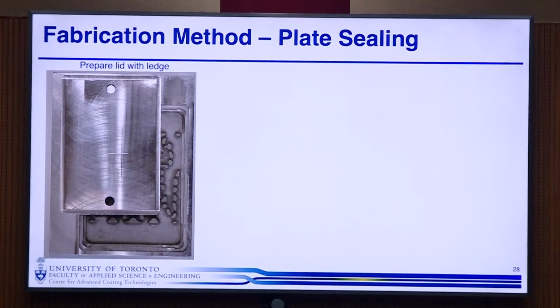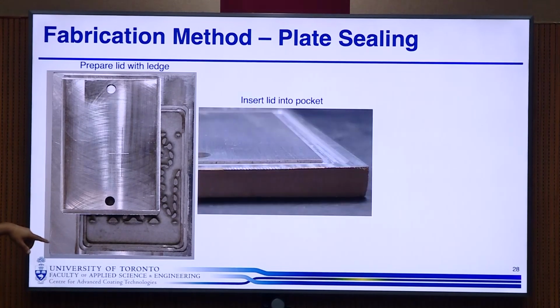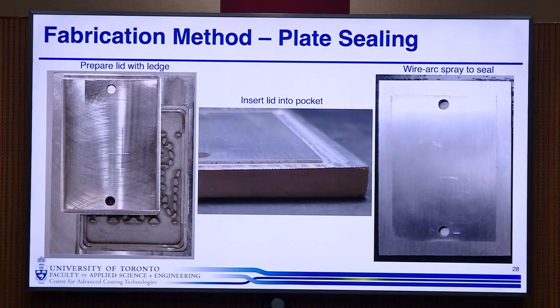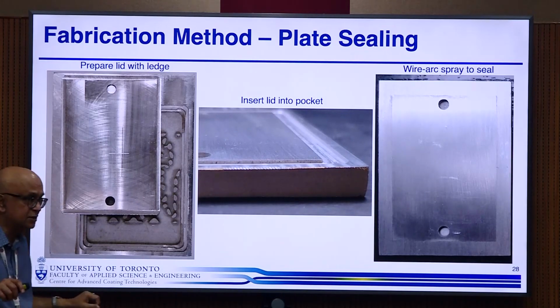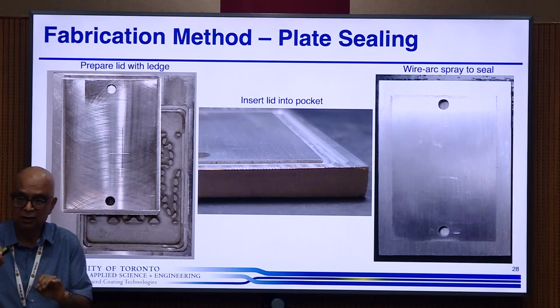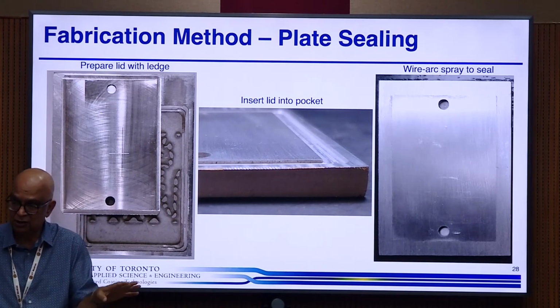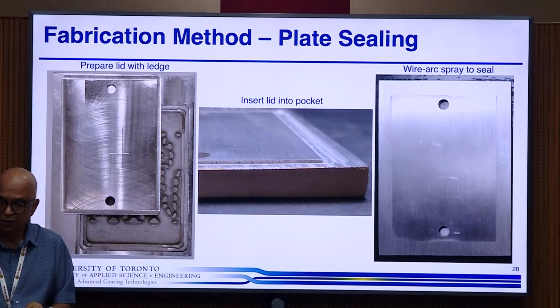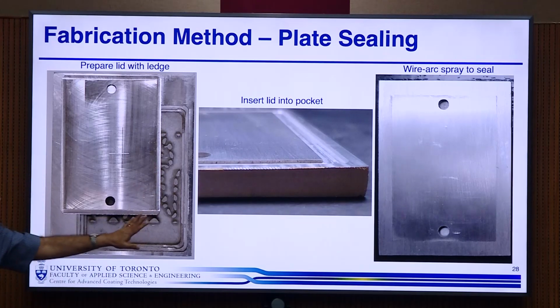Now we want to seal it. What we do is put a lid over here, and we leave a little gap between the lid and the surrounding. Then we spray metal inside that, and that seals it. So you've got about a 2 millimeter thick layer of metal inside that, and that seals the whole thing in place. You grind it down, and you essentially have just an aluminum plate with a lid.